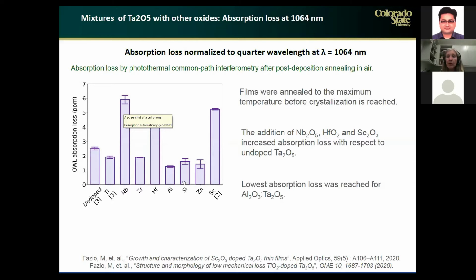Another compound that is of interest is that of zinc, which I showed you forms this ternary phase. And again, adding zinc is favorable to also reduce absorption loss. But the lowest absorption loss was obtained when we added alumina.